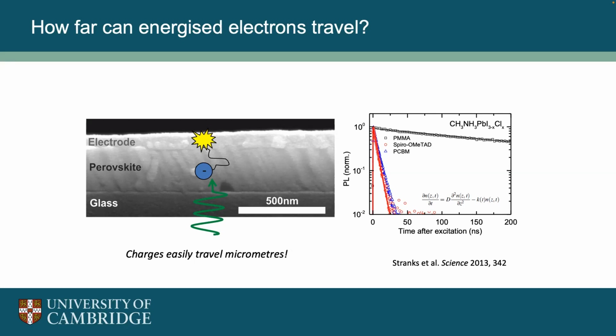In fact, we can then model this with a diffusion equation and globally model this with and without the boundary condition here, and extract diffusion lengths from this. And what we found is that these charges can travel at least a micron before they recombine. And that's important because this is about 500 nanometers thick. What it means is if we create an energized electron here, it can traverse this entire distance and be collected without losing its energy.